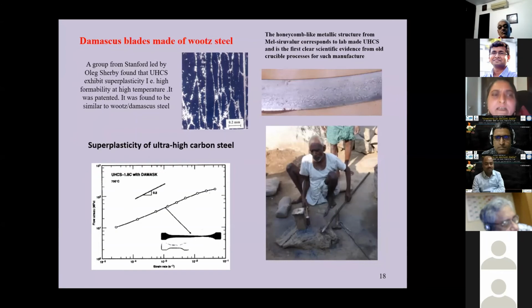Well, finally, I'll just make a couple of points before I wind up, which is that this ultra-high carbon steel was actually patented by the late Professor Oleg Sherby from Stanford, who is now no more. And he had made these studies, and in fact, I had a very nice interaction with him, which I'm reminded of now. He had undertaken studies in the 80s in an unconnected context. He had studied these ultra-high carbon steels and found that they have the property of superplasticity, which is a high formability at high temperature. And it was only later that somebody pointed out that it is very similar in composition to the wootz Damascus steel, the 1.5% carbon steel.